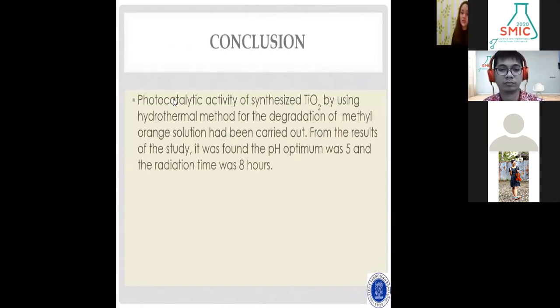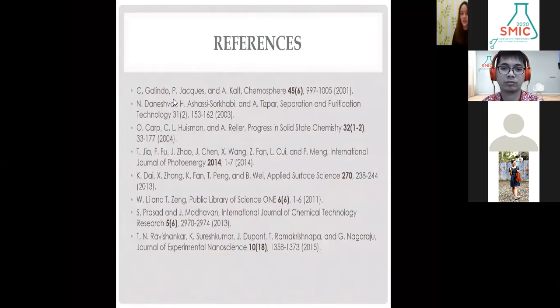Photocatalytic activity of synthesized titanium dioxide using the hydrothermal method for the degradation of methyl orange solution had been carried out. From the result of the study, it was found that the optimum pH was 5 and the radiation time was 8 hours. So here are our references, and thank you.